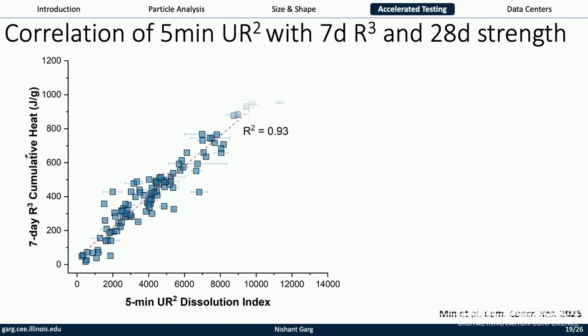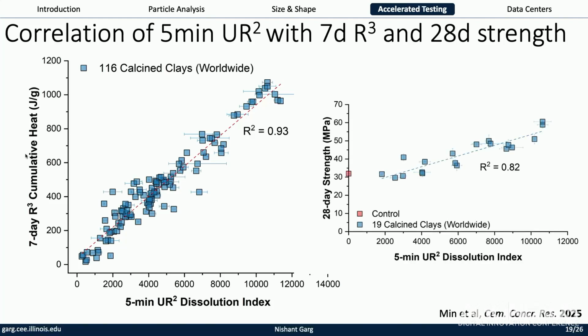with one of the samples here. This is calcined clays. It's an emerging SCM in several parts of the world. There are a few plants coming up in Africa because there's a shortage of limestone over there. By testing more than 100 calcined clays, we actually have a very nice correlation between the 5-minute and the 7-day method. And if you compare the 5-minute method with the 28-day, there also we see a very nice correlation.